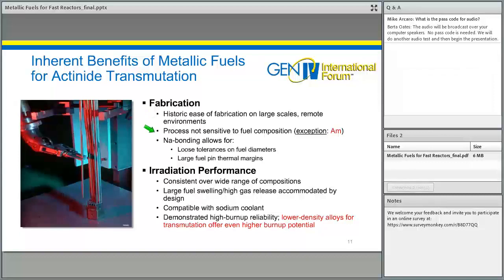The fabrication process is not that sensitive to fuel composition, and if you're doing a continuous recycle approach, there are going to be some swings in your fuel composition. Metallic fuel fabrication typically handles those quite readily, the major exception being the americium. Something's going to have to be done to address the volatility associated with americium. And sodium bonding, while it's an extra step in the fabrication process that costs a little, brings some benefits with it. Because there's excellent heat transfer between the cladding and the fuel, you don't have to worry about tight tolerances on fuel diameters needed to maintain a very small gap, and it just gives you a lot of thermal margin.